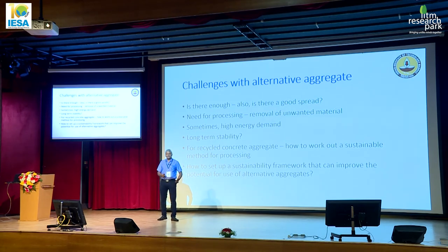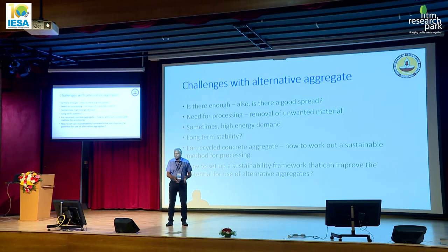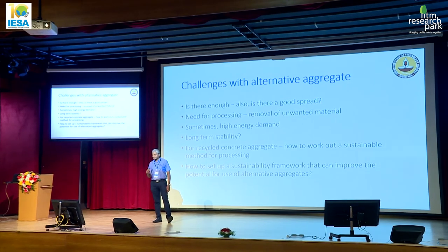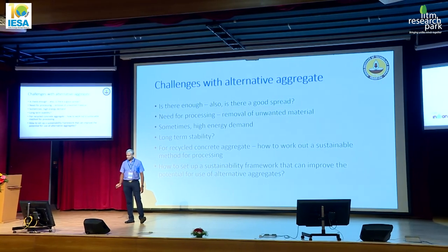As I said, high energy demand could be there. Some aggregates may have difficulties with long-term stability. We want our aggregates to be inert in the concrete. They just simply occupy the volume. They don't really do anything over the long term. They have to bind well with the cement, but otherwise, they should be inert. Otherwise, we'll get problems in the concrete durability. And again, as I said, we need to work out a suitable method for processing to achieve the lowest energy pathway to produce these alternative materials. And again, very important that we can't just say that, okay, I'm replacing some natural aggregate with recycled, so my concrete is sustainable. No, we need to evolve the right sustainability framework, get real data from these crushing units and processing units to get a true picture of what's going on.